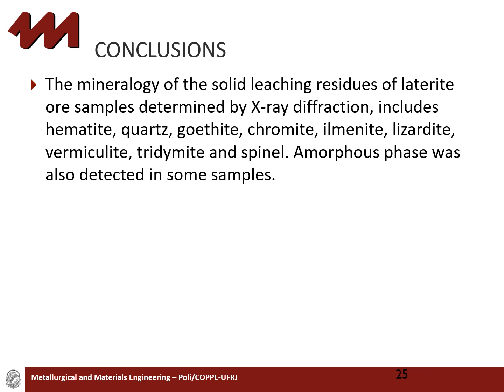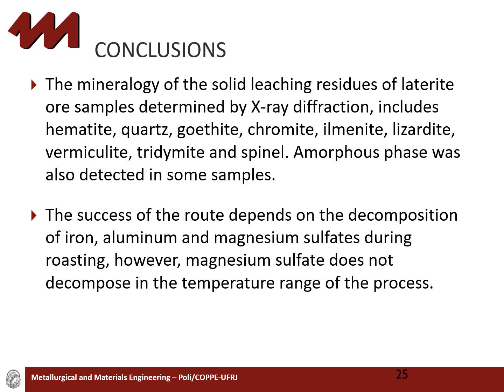Conclusions. The mineralogy of the solid leaching residues of laterite ore samples determined by X-ray diffraction includes hematite, quartz, goethite, chromite, ilmenite, lizardite, vermiculite, tridymite, and spinel. Amorphous phase was also detected in some samples. The success of the route depends on the decomposition of iron, aluminum, and magnesium sulfate during the roasting. However, magnesium sulfate does not decompose in the temperature range of the process, increasing the acid consumption.